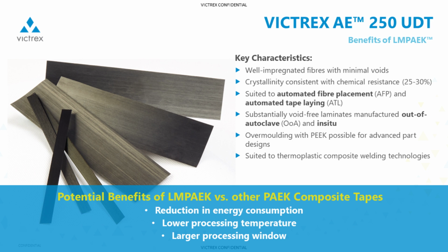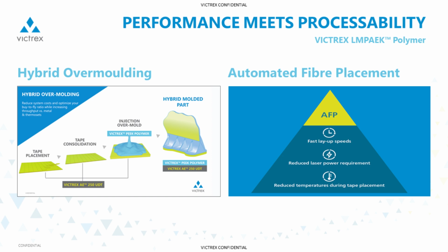And then the other thing that delta between the melting temperatures has opened up for us is the ability to design what we call hybrid overmolded parts, where we use the continuous fibers in a low melt format to provide the strength and stiffness of the part and really manage the bulk of the loads. And then we are able to injection overmold with the traditional PEEK, which then allows us to functionalize the part and add geometry that just wasn't previously possible. So it opens up opportunities to replace machined metal subtractive parts with a fairly additive composite format that drives both reduction in weight and reduction in system costs when we choose the right parts.